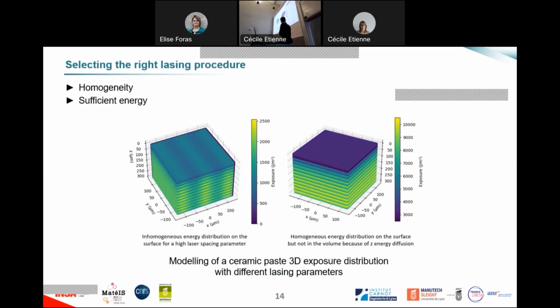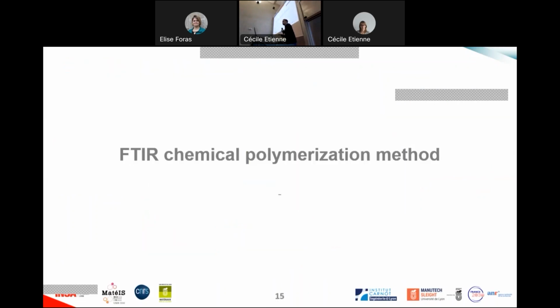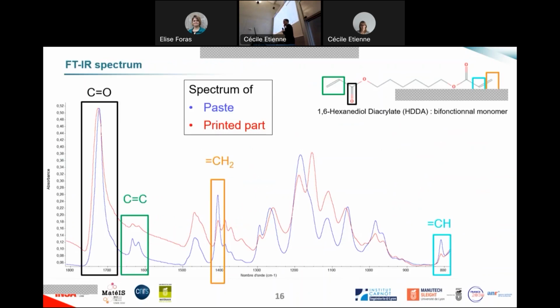Here's just an example, on the left, of some parameters that have been chosen that show non-homogeneity and could make bad samples because of that. Now I'm going to show you some results. First, how do we do chemical polymerization characterization? Using an FTIR method. This is part of a spectrum that has been made for a paste, so zero polymerization, and for a printed part that has been polymerized.